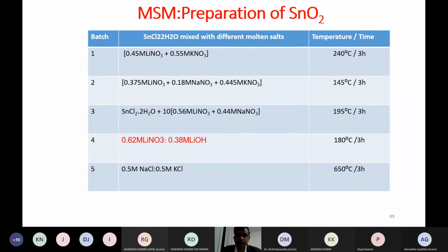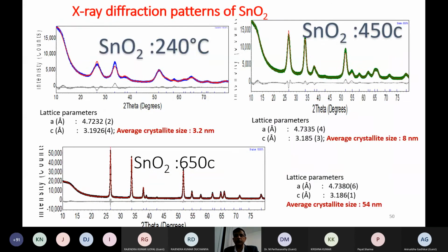So again, the tin dioxide, depending on temperature. Here is one example I can tell you: since people are working in nanotechnology, X-ray is very useful. For example, at 240 degrees we are able to see nearly 3.2 nanometer, at 450 degrees 8 nanometer, and at high temperature 54 nanometer. Automatically, we can see the broadening of the line. Whatever I discuss with X-ray is sometimes very useful, so you don't need to do TEM.